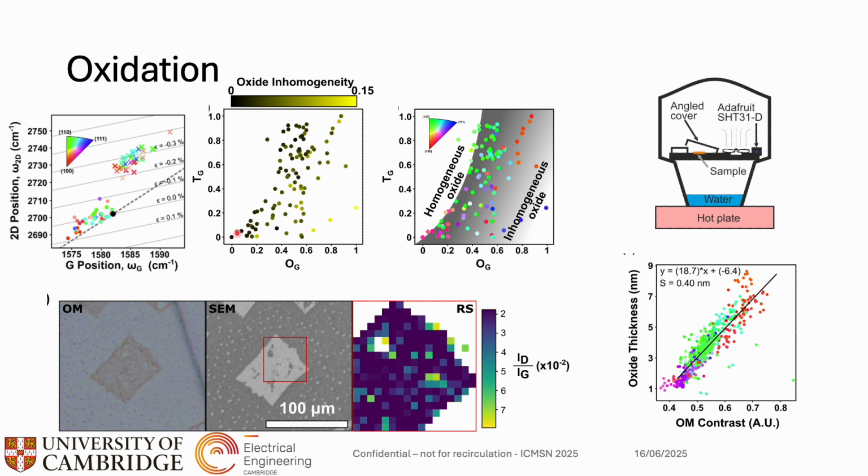The results are a correlation, but they're not particularly a great one. And you can see, for example, these 3 points down here, very heavily oxidized, but very little is transferred. And if you take a look to the right in the next plot, you can have a look and see why or what's going on here. And these points are all blue. They all tend towards 111. So in 111, it follows a slightly different trend, for example, 100, which shows reasonably linear, that the more you oxidize, the more you get off.